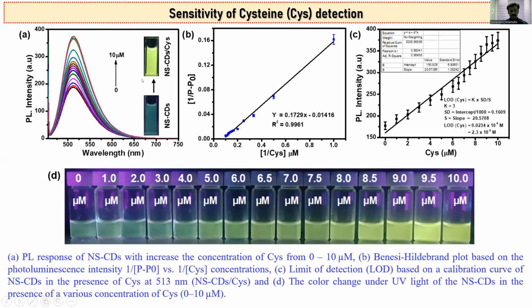So we can see from this photograph the emission changing from blue to green. Furthermore, in the plot of the photoluminescence intensity, the change occurs around 513 nanometers. It's showing enhanced efficiency. So we can calculate from this the photoluminescence intensities F0 in the absence and presence of cysteine, versus 1/[cysteine].